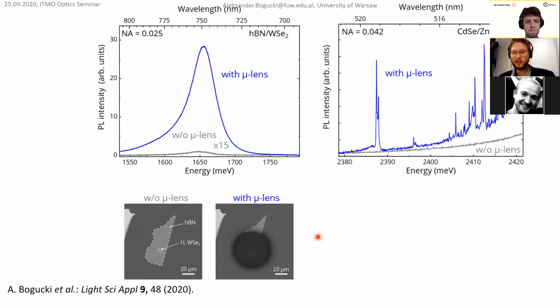Another example is with quantum dots, which I really like. This is the system of cadmium selenide, zinc selenide quantum dots. And again, without microlens, this is the gray signal. And the blue one is with microlens. And here it is very important that you can see single emission lines, sharp single emission lines.